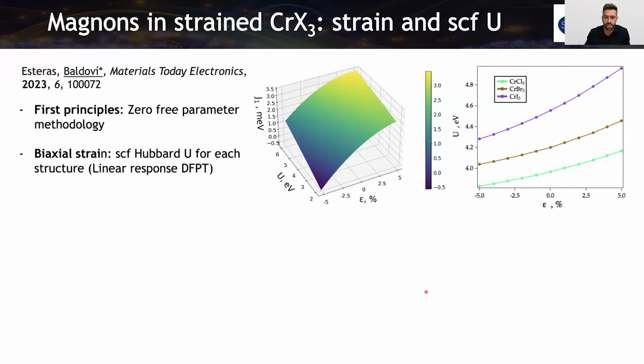And then we also want to add biaxial strain. So for each case, we're doing a self-consistent field calculation of the Hubbard U following the linear response method that is implemented in density functional perturbation theory in Quantum Espresso. And we wanted to see the effect also on each one of the exchange interactions. So for example, here, when we are applying a strain, we are computing self-consistently the evolution of the Hubbard U for each one of the points.